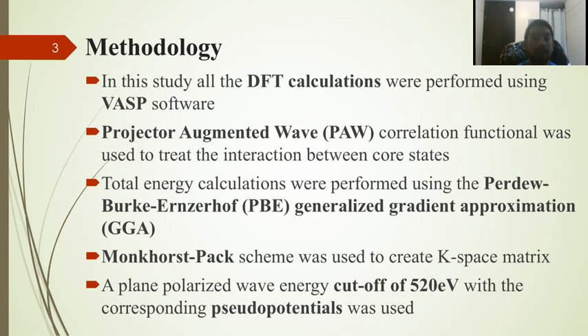Next, please. The methodology used for this calculation is DFT calculation. We'll use VASP software and the correlation functional. For the total energy calculation, we will be using the PBE-GGA approximation. For k-space, we'll use a Monkhorst-Pack 1:1:1 matrix, and a cutoff energy of 520 electron volts will be used for the PAW potentials. Next, please.